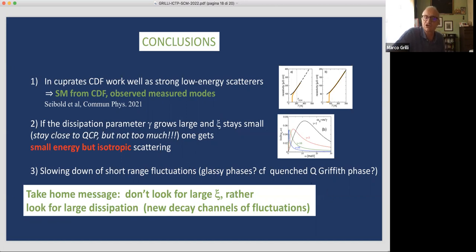So this is something which is somehow reminiscent of what Andy Millis, Jörg Schmalian, and Dirk Morr did in the case of quantum Griffiths phases, where they found that if you introduce the damping, the Landau damping, the instantonic tunneling processes which flip the order parameter inside the quantum Griffiths phases are made more and more rare, and they eventually get quenched. So essentially, this is a similar phenomenon.